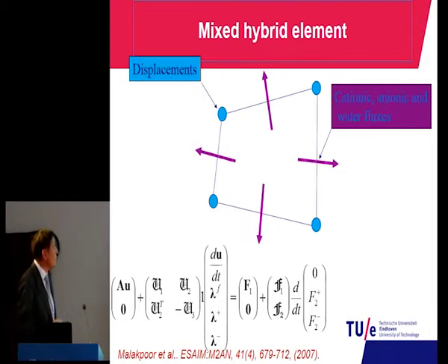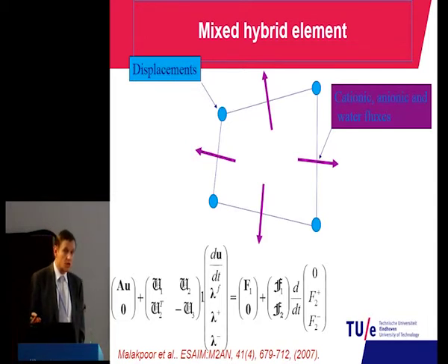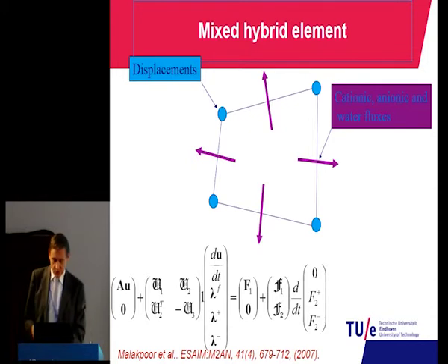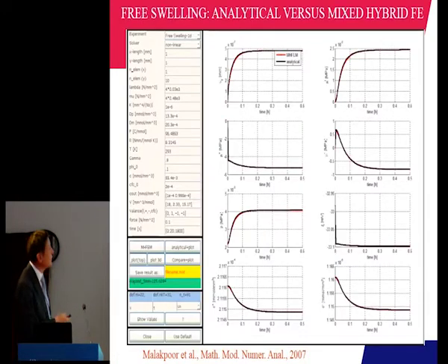And the assumption is that the whole material is electroneutral. So there is as many positive as negative, but because there are two components which are negative, namely the anions are negatively charged, but also the solid is negatively charged, there is a different concentration between anions and cations everywhere. And for simplicity, we just assume isothermal behavior, incompressibility, constancy of ionization, so no chemical reactions going on, and negligible acceleration and gravitation. So the equations that we get is basically a balance of momentum, balance of mass.